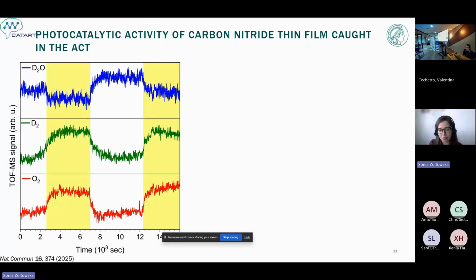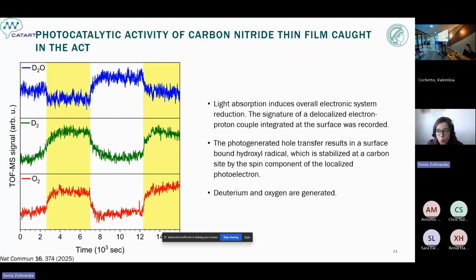But in our entire system, we had the TOF MS downstream, so we were able to follow the products during the reaction. We were following signals from heavy water, deuterium, and oxygen. And as you can see here, upon illumination with the solar spectrum, here is the block marked with yellow, the signal from heavy water decreases with also a slow increase of the signal coming from deuterium and oxygen. We wanted to confirm whether it's the photochemical character of the process, so we turned off the solar simulator and still performed the measuring, and you could see the increase again of the signal from heavy water and a slow decrease of the signal from deuterium and oxygen. But indeed, we prove formation of deuterium and oxygen during the catalytic process.